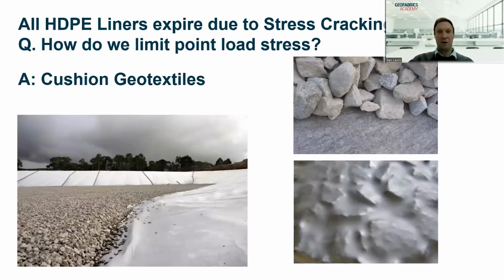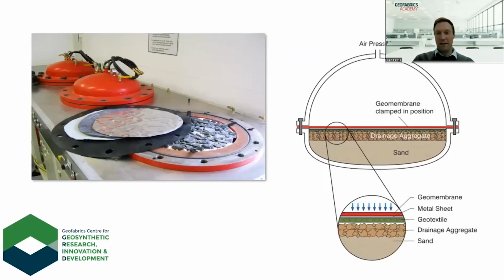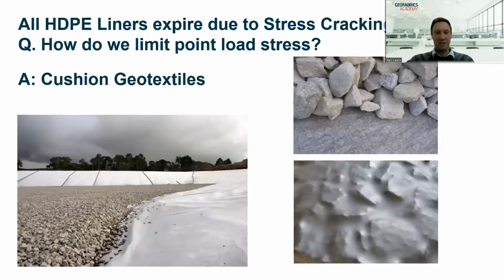all HDPE will expire at some point due to stress cracking. So if we can limit the stress cracking or improve the performance of the HDPE, it should be done. But what we do in the lab, we do a cushion test, which is effectively profiling up the membrane with a cushion geotextile, loading it up with a site-specific load and compressing it against the expected rock or drainage layer which the cushion and membrane may be in contact with. So if you've got, let's go back to this picture, you can see they've got drainage over the liner here, which has got a cushion between it, or geotextile, and the objective is to limit strain to an allowable limit to prevent cracking over time.